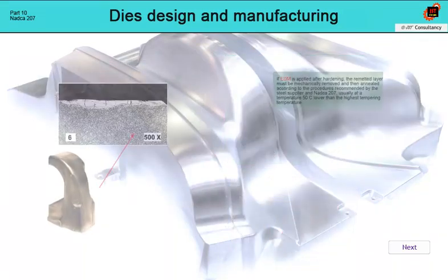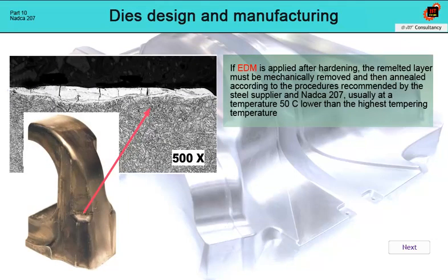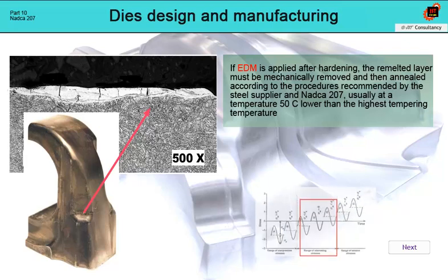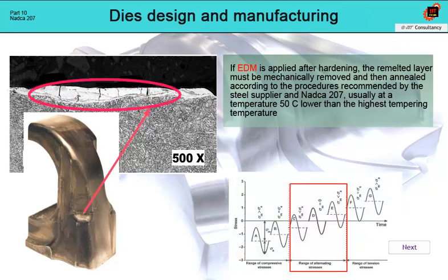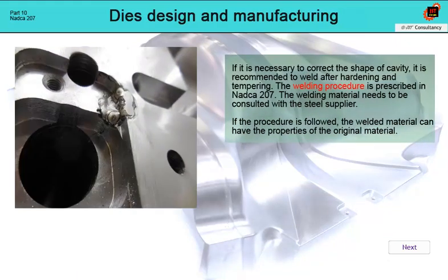If EDM is applied after hardening, which is the preferred option, then after EDM, the layer must be manually or mechanically removed and then annealed. Otherwise, it will be a source of cracks during cyclic stress from thermal fatigue. A similar problem is represented by welding.